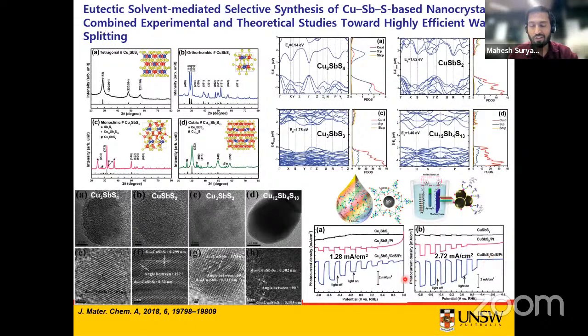You can see the performance improvement in these samples is a little bit higher than this one. Again, we can correlate that to the band gap energy of about 1.62 electron volt, which is quite optimum to harvest the maximum sunlight, whereas this compound has a band gap energy of about 0.94 electron volt. That again explains why the performance in these 2 is slightly different.